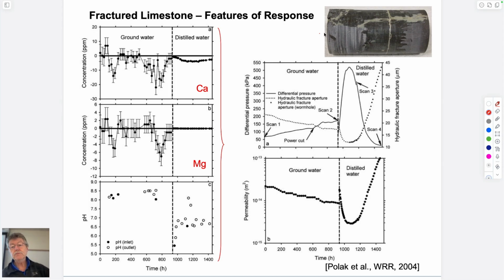So the final one, we'll just finish with this, was to do the same kind of experiment but on a limestone fracture. So this has much greater reactivity, much greater dissolution characteristics. It was done at ambient temperature, no temperature effects here. And it was flowed with groundwater, with dissolved components in it. It was in equilibrium with the rock. And then it was flushed with distilled water. So when it's flowed with groundwater, you see that the actual change in permeability, hydraulic aperture if you like, decreases by net dissolution from the fracture into the water, and then the closure of the fracture due to the action of pressure solution.